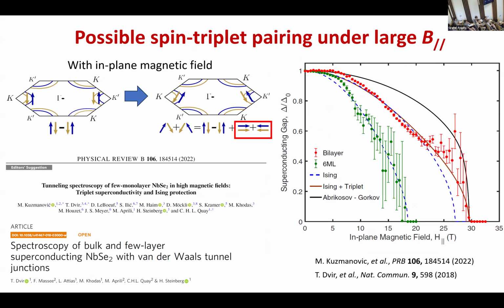Then, Clear and Hadar also carried out these measurements down to very high field, and they observed that, as he just mentioned, this is very sensitive to the in-plane field. When you apply an in-plane field, the spins start to tilt, and you can think of these tilted components as a spin triplet channel. From this experiment on bilayer, indeed they see that the standard Ising pairing cannot follow this very nicely, especially in the high field range. Only if you add this spin triplet pairing into consideration can it more easily describe how the gap evolves with a strong magnetic field.